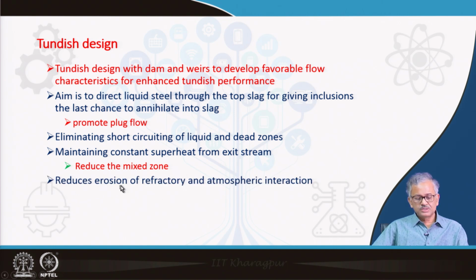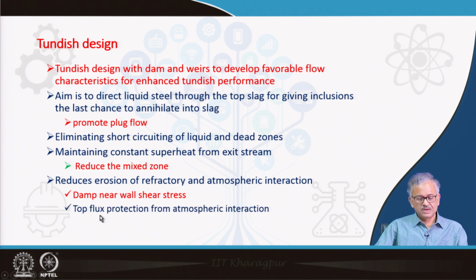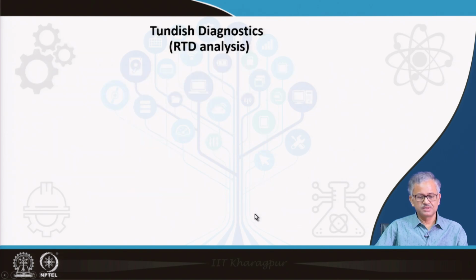And also reduce the erosion of the refractory and atmospheric interaction. So, you should design the fluid flow in such a way that it does not have much interaction with the refractory wall, that is, the shear stress at the wall should be as low as possible, such that you do not have much erosion. And atmospheric interaction you can avoid by using the slag. And also dampen the near wall shear stress, as I said, and use top flux to protect from atmospheric interaction, as I said, that is also really required. So, these were the aims.